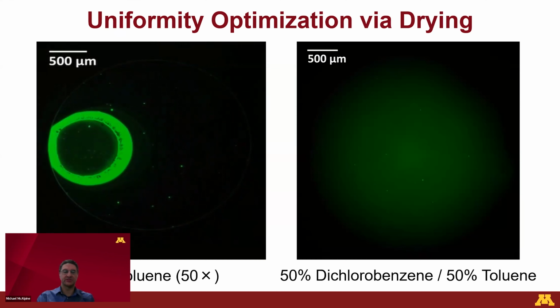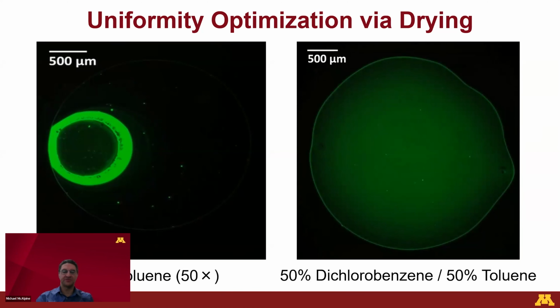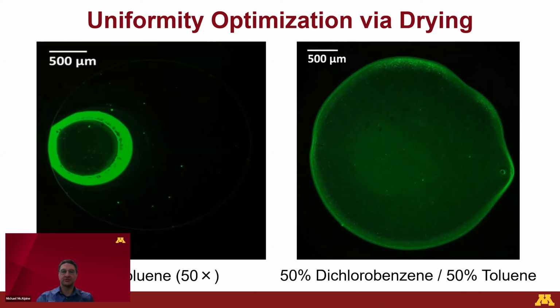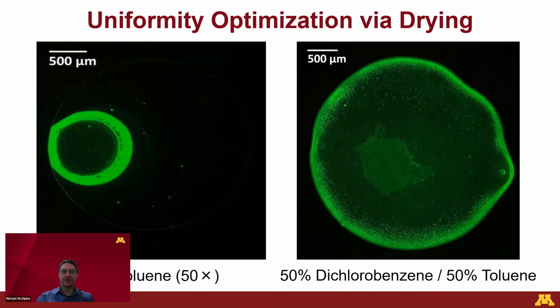And that can lead to pinholes and other types of defects in the device. And so it's undesirable. So the trick here is, if you can mix in a co-solvent, an old chemistry trick. You have a co-solvent which has a lower surface tension. You mix that in. So instead of having pure toluene, you actually have a mixture of two solvents. Then this magical thing happens where you have this effect called the Marangoni effect, and it counteracts the coffee ring effect. And now suddenly the drying process is substantially more uniform, and you get this nice uniform distribution of particles throughout the droplet. I mean, still obviously not perfect, but much better than it was in the first video. And that allows us to get better device yield and device performance.